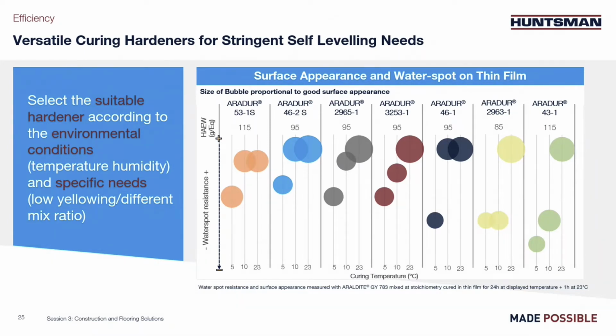So the same hardeners shown before have been tested at different curing temperatures, 5, 10, and 23 degrees C. This is mentioned in the x-axis. Each column represents one product. The higher the bubble is, the better the water spot resistance is. The size of the bubble relates here to the surface appearance, and the bigger, the better.